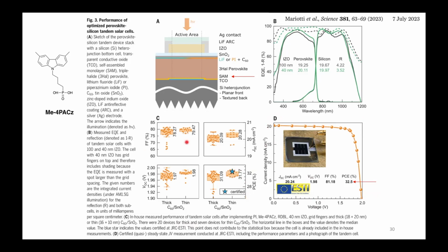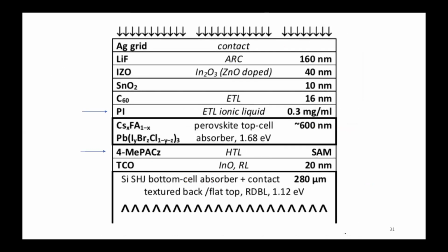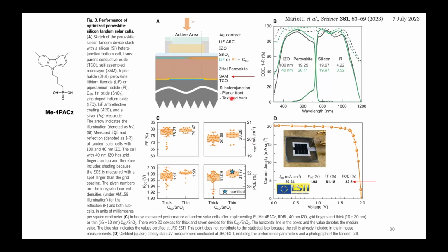There's also a patent on this molecule, especially since various groups use it as the hole transport layer. So here you have the whole structure. You can try to look at the components, and you see that they're all very, very thin layers on the nanoscale. But on the bottom, we have the silicon. It's extremely thick relative to the rest. It's 280 micrometer. But there's a textured back. This means we have a pyramid structure on the back of the silicon.